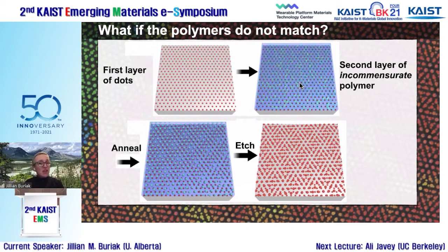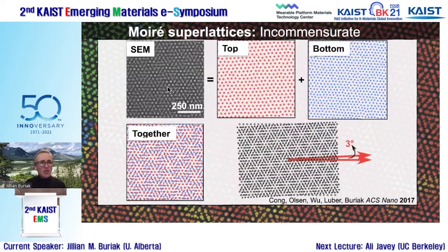The second block polymer says, no, my native spacing is this. So if I'm going to lower global energy, I'm actually going to adopt a slight offset of rotation and adopt a Moiré superstructure. And so again, Brian took these SEM images, and Cong, by the way, came to me and said, I see triangles everywhere. Brian wrote an algorithm that would take these SEM images and automatically separate the top layer from the bottom layer. And just to show you that this is real data, underneath this 250 nanometer scale bar, you can see 3 fat dots and 3 small dots, and you can see them in the corresponding separated red and blue images.